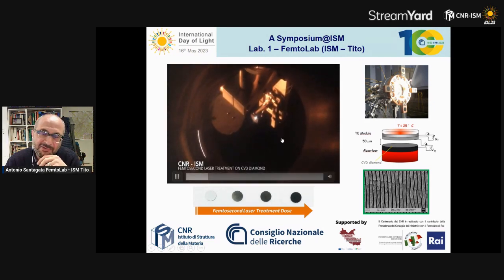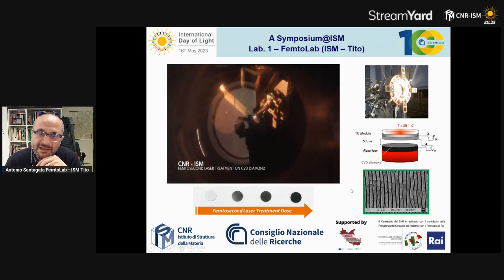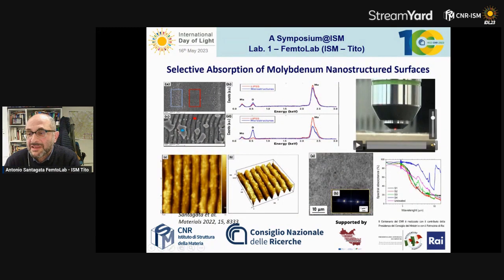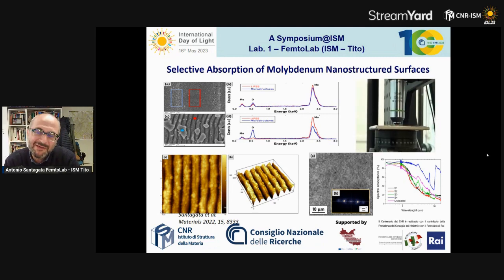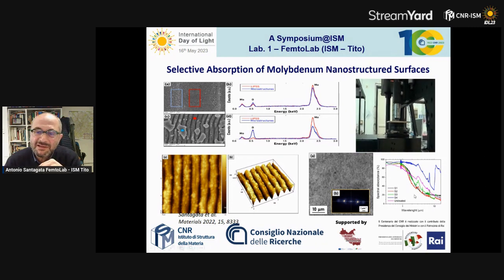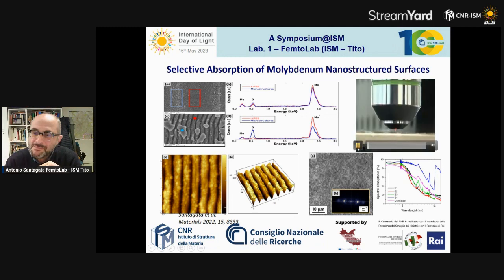We can get the nanostructures in vacuum, but even by using a workstation, which actually provides the nanostructure by focusing the laser beam onto the sample in air, in atmospheric environment. And in this case, we have seen that the molybdenum nanostructures induced by femtosecond laser can actually vary the optical properties by enhancing the selectivity in absorbance of the light. And apart from the nanostructures, we can have even nanoparticles that can be deposited on the nanostructure.